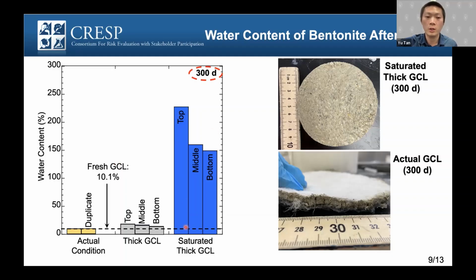And for the saturated condition, we put water at the top to make the thicker GCL saturated. So the water content is high, and this is the figure of the GCL after 300 days of interaction. You can see that it formed gel structures. It should be impermeable.